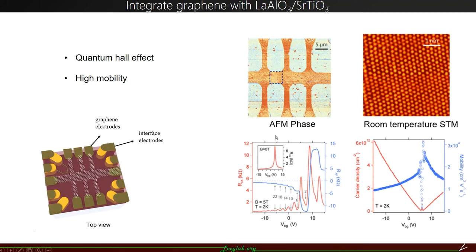Our goal is to integrate these two novel systems together. So we put graphene directly on top of LAO-STO and pattern graphene into a Hall bar structure. And then we contact the graphene and LAO-STO by fabricating gold electrodes. Here is an AFM image of the device, and we did room temperature STM, which shows our device is atomically clean.